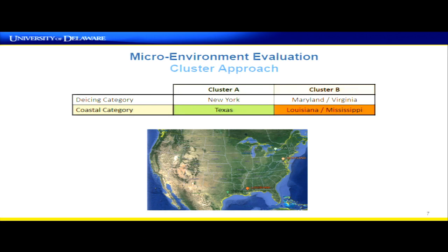As we move into looking at the microenvironment, the approach here was what we called a cluster approach, where we picked 4 geographic regions and we established bridge clusters, which were really groups of about 20 bridges within a 50-mile radius of one another. And these were selected looking at outliers in performance. So for example, this cluster near Buffalo, New York is not just good performing weathering steel, but it's good performing weathering steel in an area where there's 90 inches of snow a year, there's many major interstates, heavily salted, high ADTs, and it's still performing well. So these were things we wanted to look into more carefully.